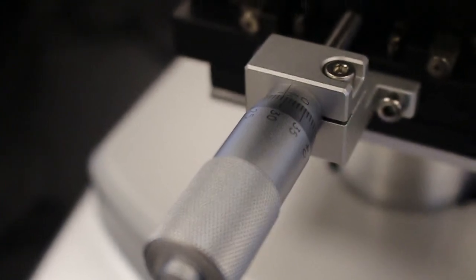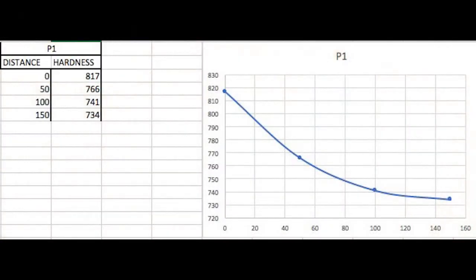We make sure to sand the piece well to allow us to do the test correctly from the shore to the center. We did the test 50 micrometers to the shore to the center. In the piece 1, we got in the shore 817 and it decreased to 734. In the piece 2, we got in the shore 900 and in the center 854. And in the piece 3, we got 887 and it decreased to 794.